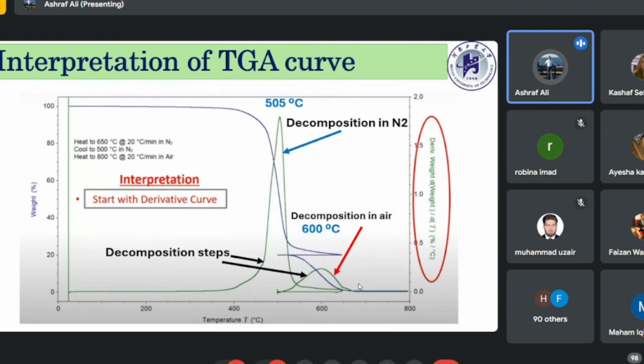On this curve, you can see that on the left hand side we have the weight loss percent, on the right hand side we have the derived weight of the material. So once again, if you look toward here, start with the derivative curve. Now there are two curves. The first one is the TGA curve, and the green curve is the derivative curve, that we have derived from this one. Now look toward the decomposition steps here. The first decomposition step, and there is a second decomposition step. The first decomposition step is the decomposition in nitrogen, which starts at 505 degrees C. The second one is decomposition in air, which is at 600 degrees C.